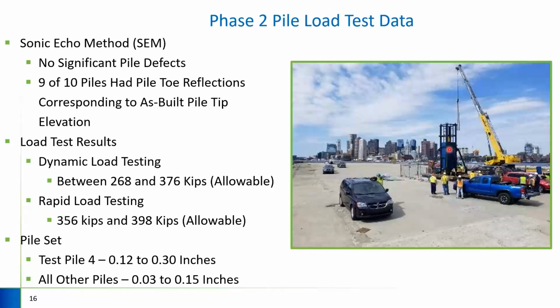For the pile set itself, test pile 4 was the one anomaly where we got up to about 0.3 inches of movement, which is still well within the limits for this structure. And for that, you should note that we tested that pile in the rapid load test to about 400 kips. So that's about 30% higher than the design load, which obviously makes sense that we're getting some additional movement. And then the remainder of the piles, similar to phase 1, ended up seeing sets of less than 0.15 inches, indicating that they could achieve additional capacity.